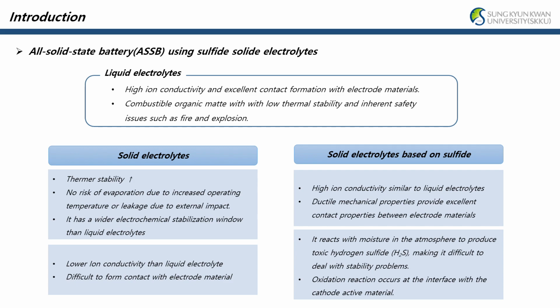A sulfide solid electrolyte has high ion conductivity like a liquid electrolyte, and its ductile mechanical property provides excellent contact between electrode materials. The problem is that it reacts with moisture in the atmosphere to produce toxic hydrogen sulfide, so care must be taken not to be exposed to the atmosphere during manufacture, and oxidation reactions occur at the interface with the cathode active material. I'd like to do some research to solve this second problem.